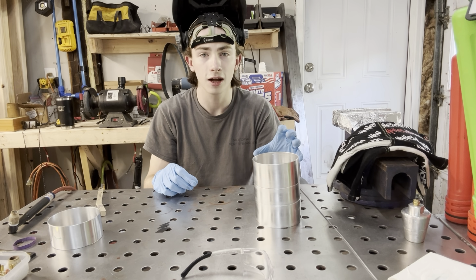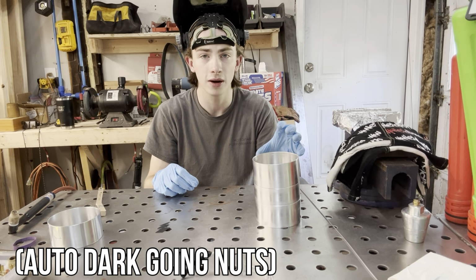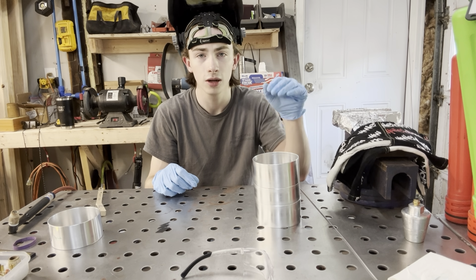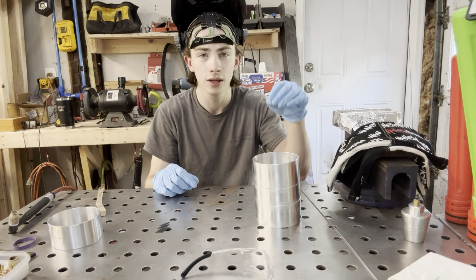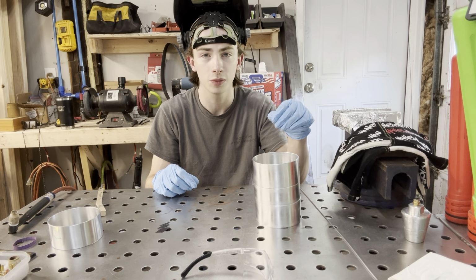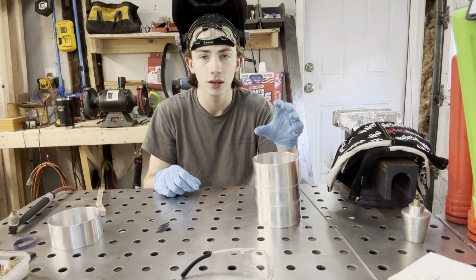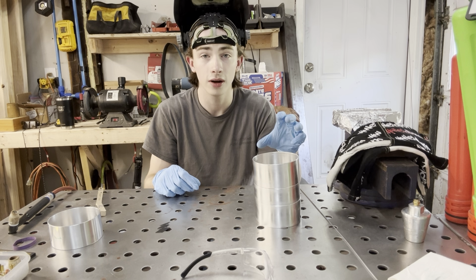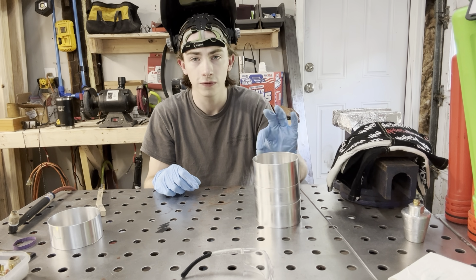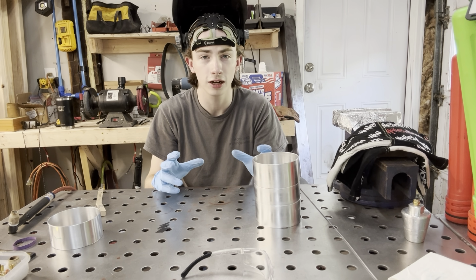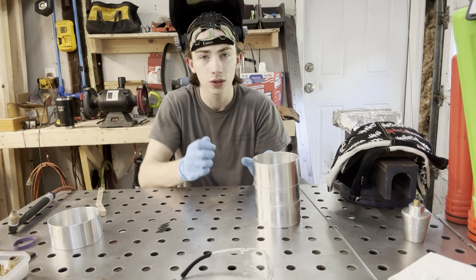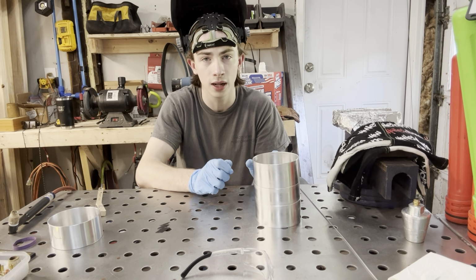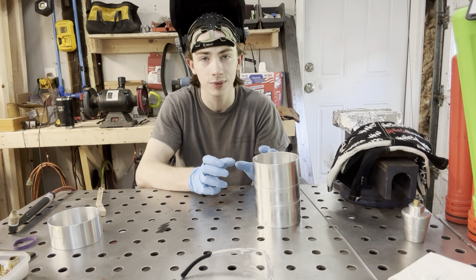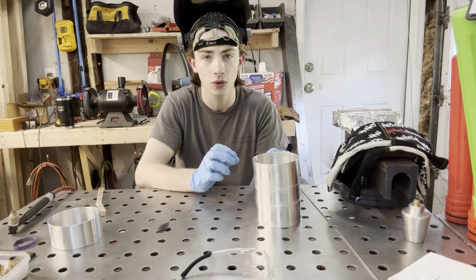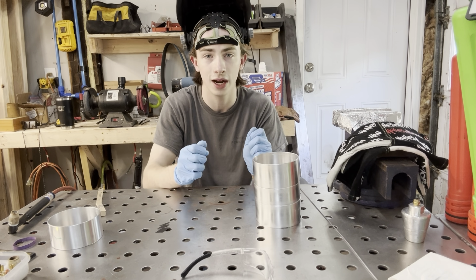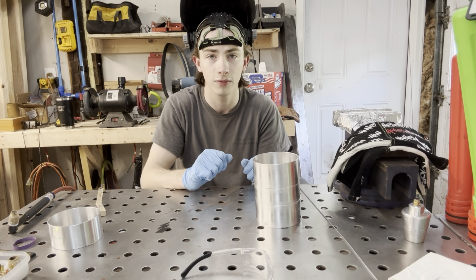Now we're ready to tack up our parts. One of the nice things about aluminum is that that oxide layer protects the inside of the puddle, so we won't need to purge the part. As I told you, aluminum likes filler rod, and without enough filler rod, it likes to crack. Fuse tacks, when you're tacking your part up, can be difficult, so I like to run a short fusion weld, and even then, sometimes they still crack, but it's enough to hold it together so that we can get our other hand free and add some tacks with filler.